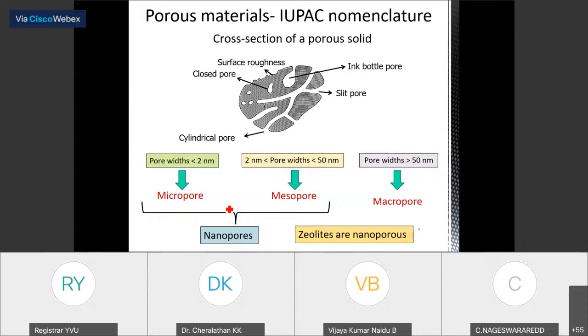So based on this IUPAC nomenclature, they can be called as microporous, mesoporous, and macroporous. In the case of microporous materials like zeolites, the pore diameter or pore width will be smaller than 2 nanometer. The materials which are having pores smaller than 2 nanometer will be called as microporous materials. And the materials which are having widths greater than 2 nanometer and within 50 nanometer will be called as mesoporous materials. And if the pore width is greater than 50 nanometer, they can be called as macropores.